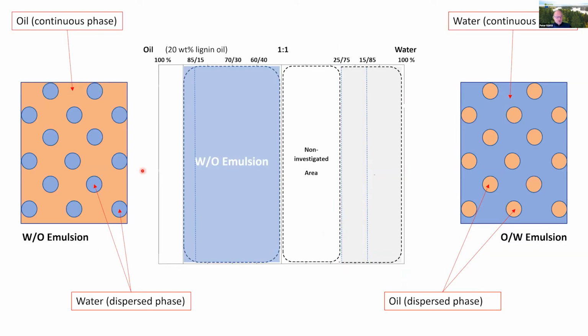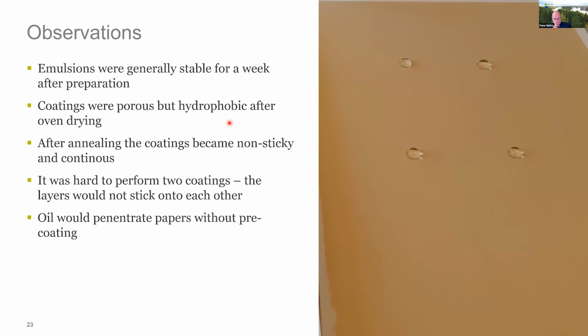If we look at water in oil, you would have the water as the dispersed phase in the oil phase. In oil in water, you would have it the other way around, oil as the dispersed phase. And this is usually what you think about. We have actually tried both of these, but I will only talk about this one here. Observations afterwards, you actually get a quite nice surface like this. We could also see that the emulsions were generally stable for a week after the preparation, so we can actually handle them, but it could be better, of course.